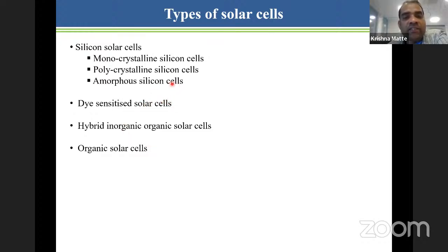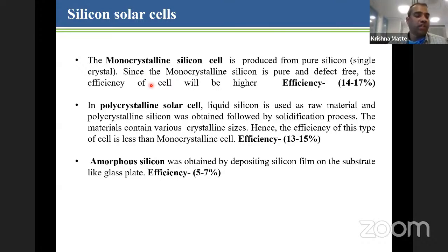And the other three are still at the research level, and some of them are commercialized to some extent, but not the way silicon solar cells are commercialized. In the case of silicon solar cells, there are two to three different silicon varieties. One is monocrystalline, another is polycrystalline, and the other is amorphous. Whether you take monocrystalline, polycrystalline or amorphous, the conductivity of these devices would vary. Monocrystalline will be really conducting because of the pure silicon, and you'll get band-like transport. In polycrystalline silicon samples, because of the defects and the polycrystalline nature, the conductivity would not be as good as monocrystalline.